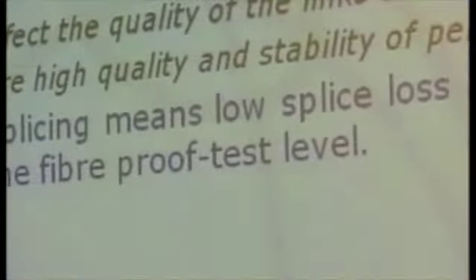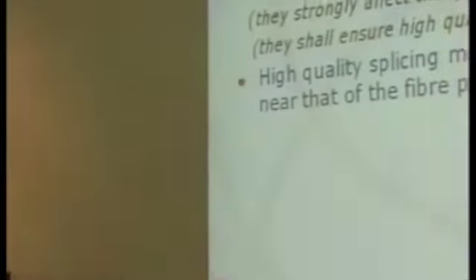The idea of applying a proof test during fiber manufacturing is to split the fibers into good pieces and use only the strongest part of the fiber that was manufactured. When we put two of these stronger fibers together and do a splice, we want the splice to be as strong as the fiber. The splice is a point that connects two fibers, and it also needs to have tensile strength near what we expect in other positions of the fiber. The splice shall be stable over the design life of the system, and under the environmental conditions we expect the system to experience during this lifetime.